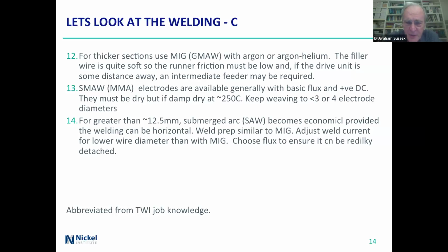Weld prep, pretty similar to the MIG, and just adjust the weld current down for the lower wire diameter than the MIG, and choose the flux to make sure that it can be readily detached - my spelling is terrible.